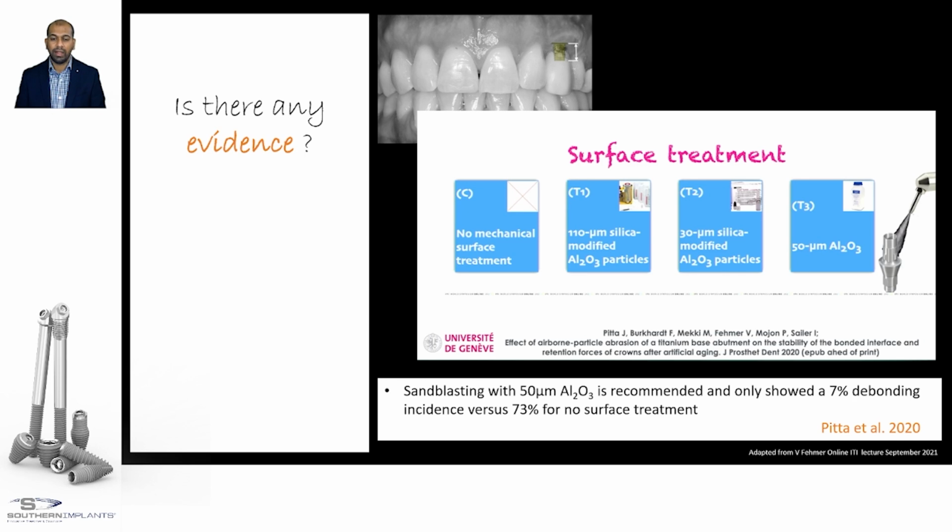They found that when we used the 50 microns of aluminum oxide particles, it gave us the best bonding result, with only 7% debonding versus 73% debonding when no treatment was done. So should we sandblast the titanium base abutments? And the answer is yes, we should. And we also know how we should do it: with 50 microns of aluminum oxide.